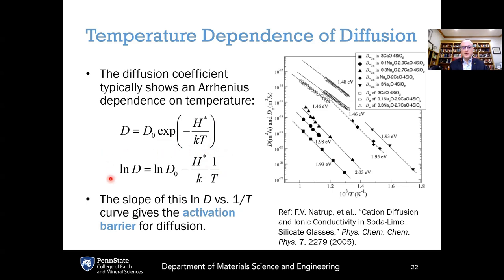So taking the logarithm of the Arrhenius equation effectively linearizes it. You've got the natural log of D is equal to our y-intercept, which is the natural log of D0, and then our slope, which is minus H star over k, times our x variable here, which is 1 over temperature. So we're plotting the logarithm of D versus 1 over temperature, and then the slope here would give you the activation enthalpy for that kinetic process, in this case for diffusion. The D0 would be the limit of the diffusivity as the right-hand term goes to zero. This right-hand term goes to zero when the temperature goes to infinity. So this D0 is the limit of the diffusion coefficient at infinite temperature.